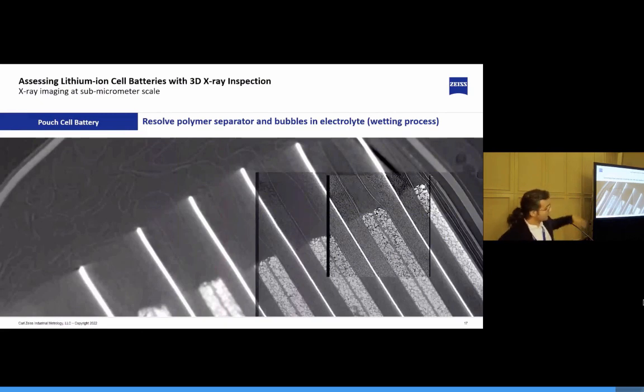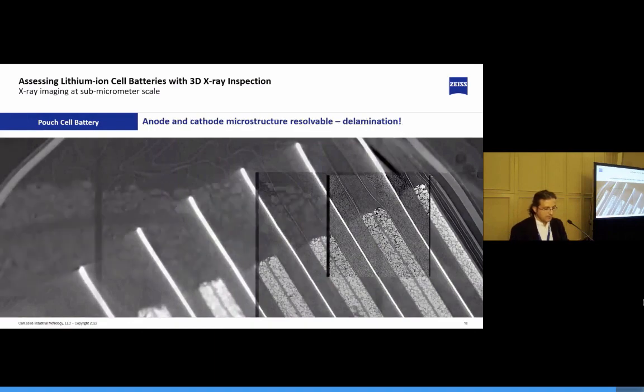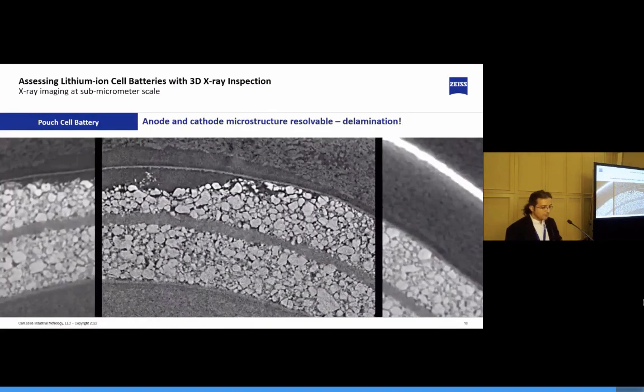And you can also see how you can overlap the different scans, because you have the registration, the coordinate information in 3D space, and you can register one scan on top of the other to compare. And it's really impressive when you start zooming in to see the granular microstructure of the graphite anode in this case, as well as the mixture of lithium cobalt oxide in the cathode. You can notice all the microstructure and trails of delamination in this case.